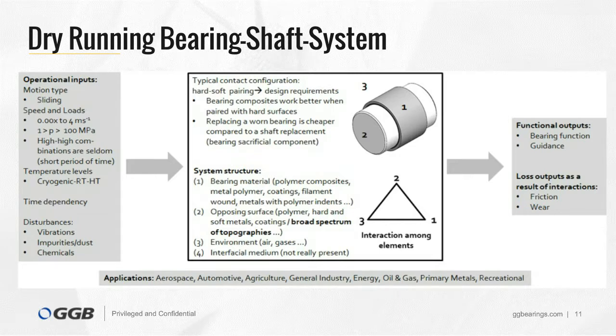A high combination of high loads and high speeds is seldom, and when it occurs, it normally is of short duration. A constant operation at high conditions normally destroys the contact due to overheating. The temperature range of such an application can also be manifold, so we have temperature ranges from cryogenic to high temperature applications.